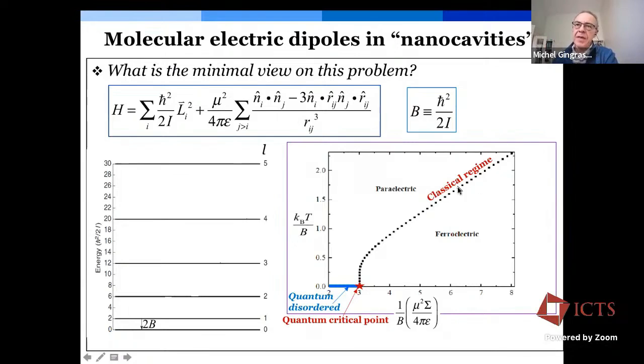And so in the classical regime, where the moment of inertia is very large, one finds that the critical temperature between the paraelectric phase and the ferroelectric phase is proportional to the dipolar energy scale. In this classical regime, the phase boundary lives on a straight line extending to infinity for infinite dipole interaction. As one decreases the moment of inertia, or increases the rotational constant, the critical temperature decreases up to a point where one reaches a quantum critical point,